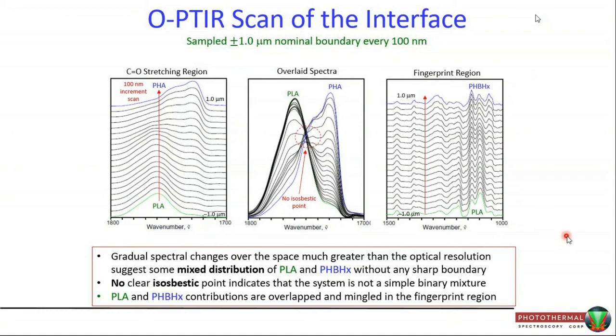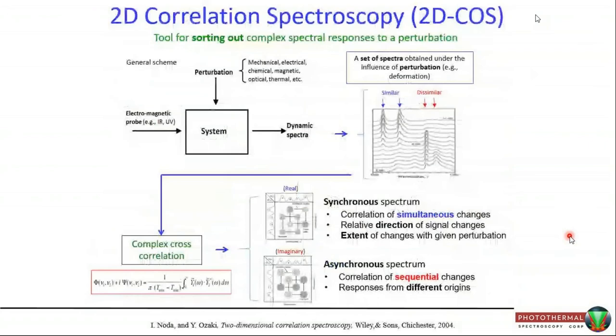Now, in order to analyze a set of spectra like this, we use additional data sorting technique called two-dimensional correlation spectroscopy. 2D correlation spectroscopy is basically a tool to sort out complex spectral response to a given perturbation. In our case, the perturbation is the position that we probe the IR spectrum. So if you change the position from one part to the other, spectra will change. And then notice that some part of the spectra will change simultaneously in a very similar way, and other part of the spectra changes in a somewhat dissimilar sequential manner.